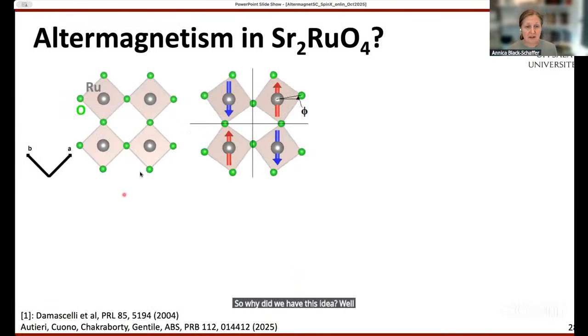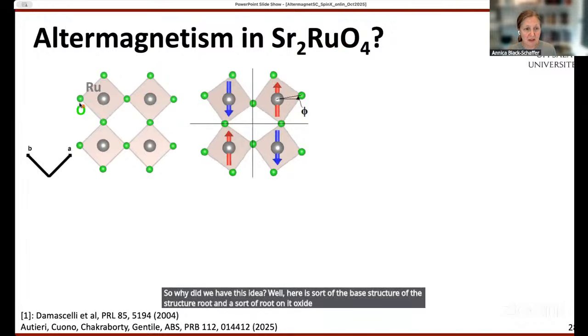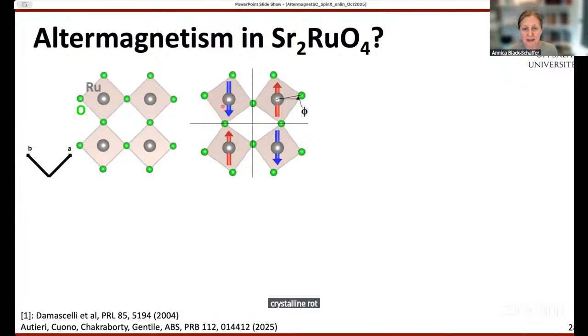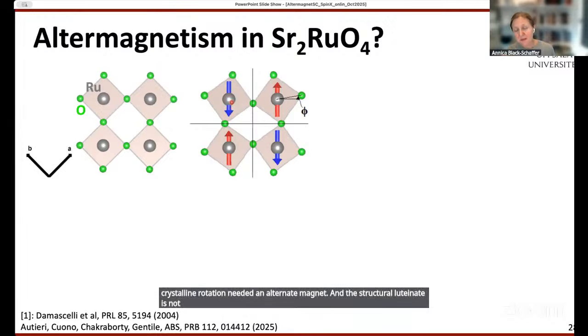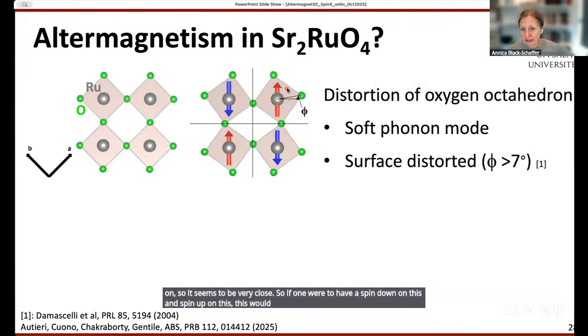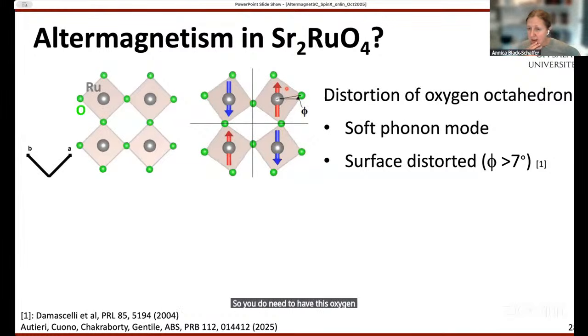So why did we have this idea? Well, here is the base structure of strontium ruthenate, the ruthenate oxide plane. We have ruthenium atoms here and oxygen here. And if one were to rotate these oxygen cages a little bit, you get the crystalline rotation needed in the altermagnet. Strontium ruthenate is not magnetic, but it seems to be very close to magnetic. It is speculated to be a ferromagnet, antiferromagnet, and so on. So if one were to have a spin down on this and spin up on this, this would actually be an altermagnet. So you do need this oxygen distortion.